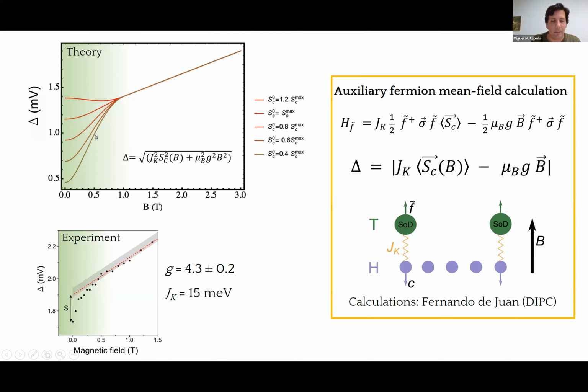But when we have small magnetic fields, this first term is also important and basically leads to different behaviors depending on the particular magnetization of the system, which is exactly what we see.